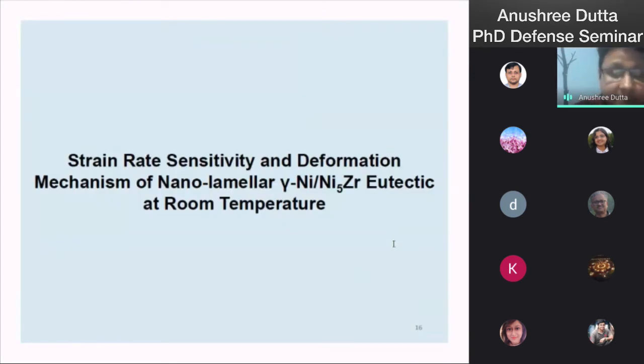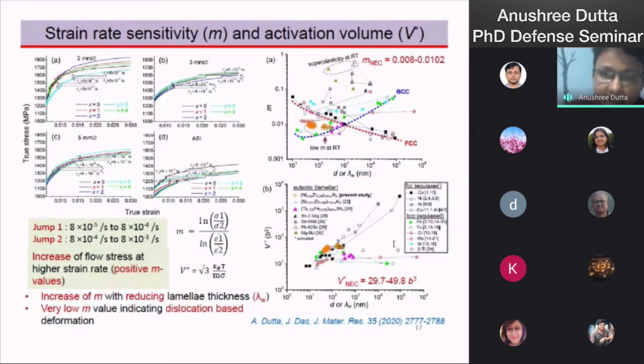Now, my second chapter is strain rate sensitivity and deformation mechanism of nanolamellar gamma nickel Ni5Zr eutectic at room temperature. The strain rate sensitivity and activation volume are measured using the strain rate jump test. Two jumps are given. In the first jump, the strain rate varies from 8 into 10 to the power minus 5 per second to 8 into 10 to the power minus 4 per second, and in the second jump, from 8 into 10 to the power minus 4 to 8 into 10 to the power minus 3.